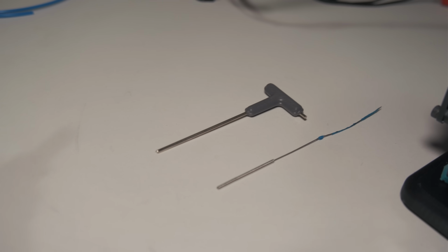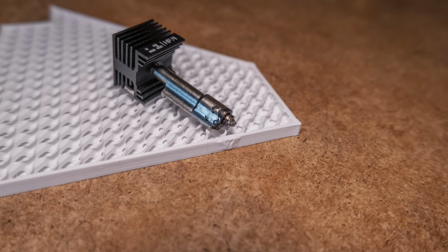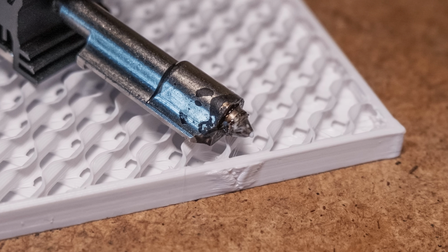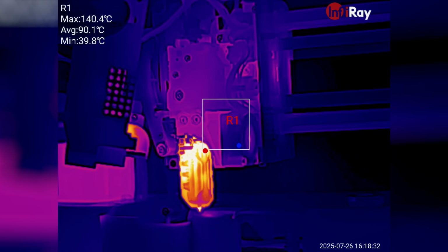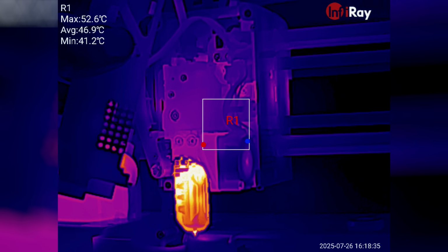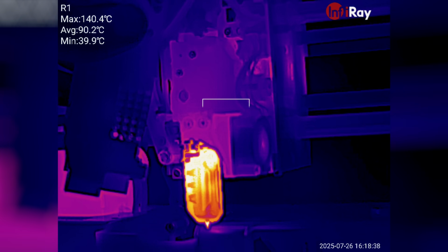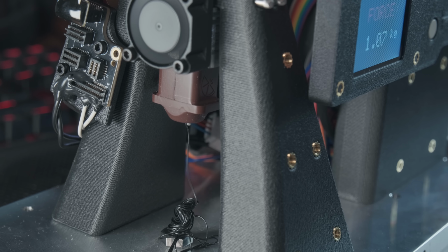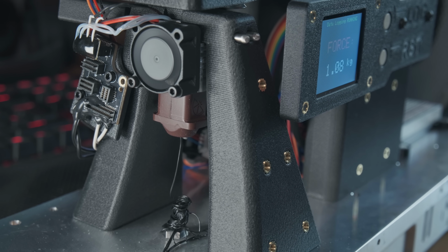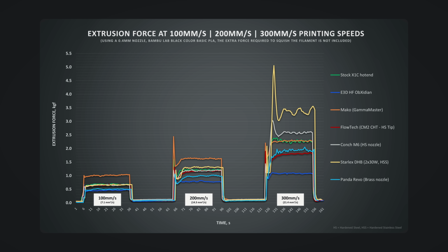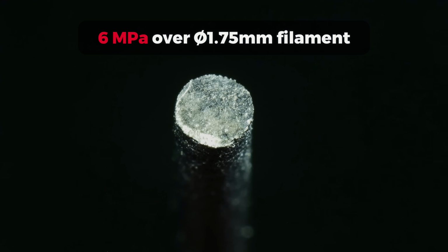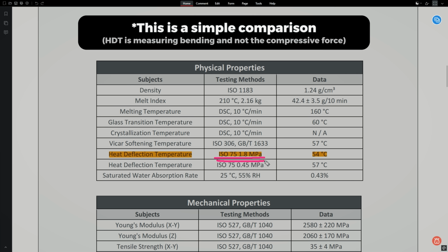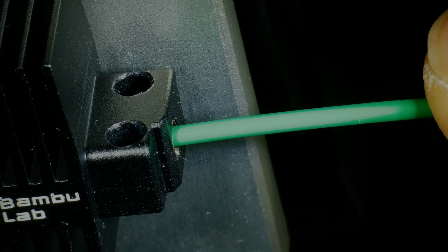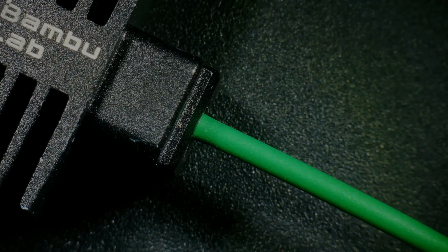If you have tried printing PLA at 45 degrees Celsius chamber temperature, you have likely jammed your hot end. At that chamber temperature, the heatsink section of the hot end is simply not capable of dissipating the heat transferred from the much hotter heat block, which typically sits around 220 degrees Celsius. In the past, I tested how much force it takes to extrude this PLA filament through different hot ends. While it may not seem like much, a force of 1.5 kilograms translates to roughly 6 megapascals on the filament's cross-section. This is about 3 times higher than the value listed in the datasheet at 54 degrees Celsius. As a result, the filament begins to deform under the extrusion force, expand, and ultimately jam the hot end.